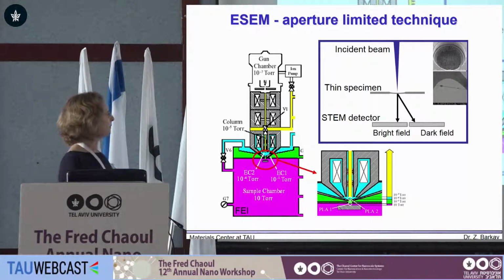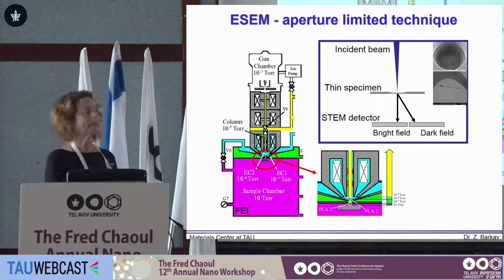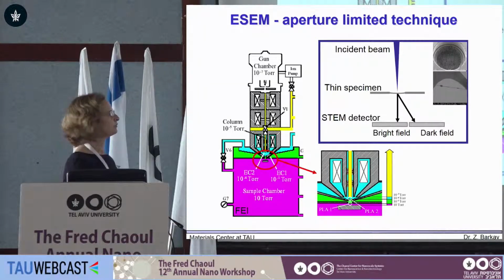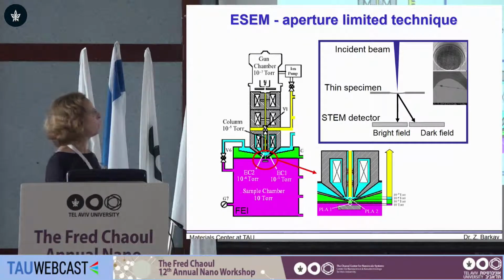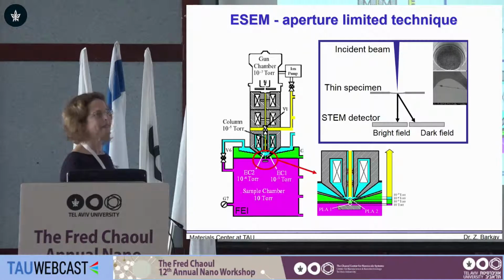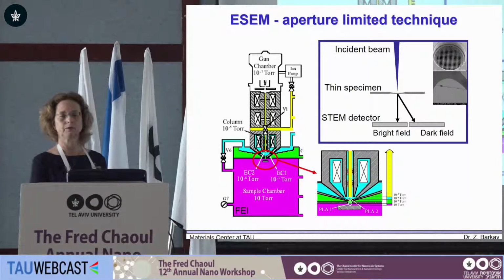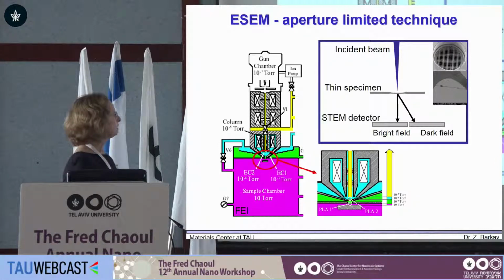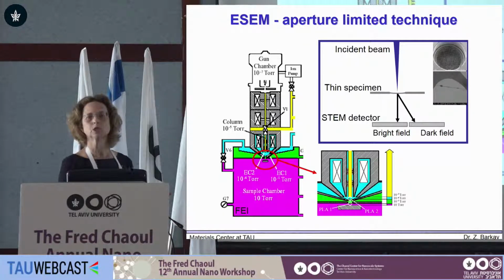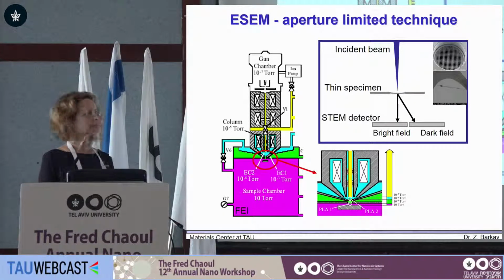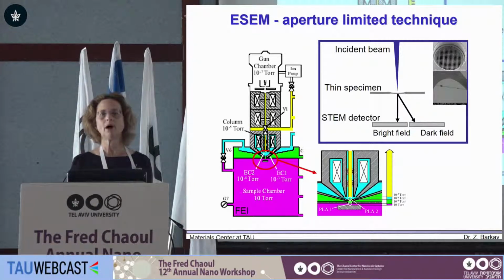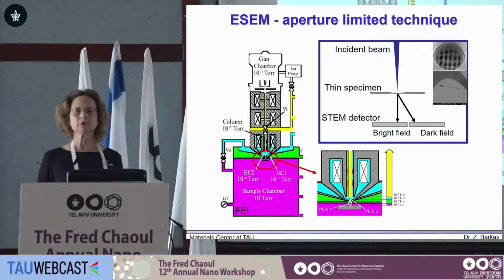In case the sample is thin enough, we can have a configuration very much like transmission configuration, so we have a thin sample, use a TEM grid, and get information in bright field or dark field. Here is a TEM grid, and an example of a wire on which there is some condensation of vapor. Basically, the images we obtain in SEM or TEM are like 2-dimensional images.